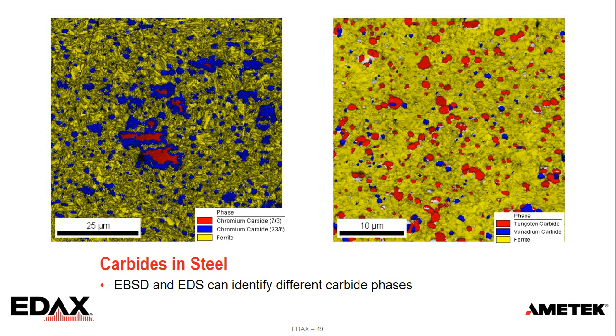The final one I'll take goes back to which polishing method you use to get this data. I'd say most of these, or probably all of these, were collected with samples that were mechanically polished down to colloidal silica, either a 0.02 or a 0.05 final polish slurry. If you're interested more in that, we have saved webinars specifically for sample prep. We are starting to do more ion beam preparation to experiment, particularly for retained austenite, to see if that has an effect, but that's just work that's starting.